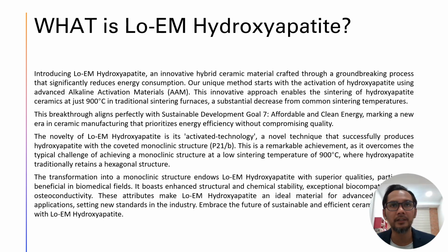What I want to mention right here is that basically for hydroxyapatite using the conventional method, we used to sinter at 1200 degrees Celsius to 1280 degrees Celsius. Normally, we achieve the hexagonal structure. We can achieve the monoclinic structure whenever we increase the temperature up to 1400. But there is another drawback where we will lose the property, the decomposition of the hydroxyapatite itself. Okay, so this transformation into a monoclinic structure endows low M hydroxyapatite with superior performance benefits in the biomedical field. So I think this is one thing that everybody in the medical device or medical ceramic is looking for.